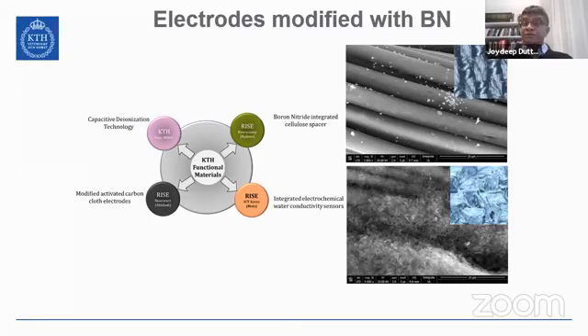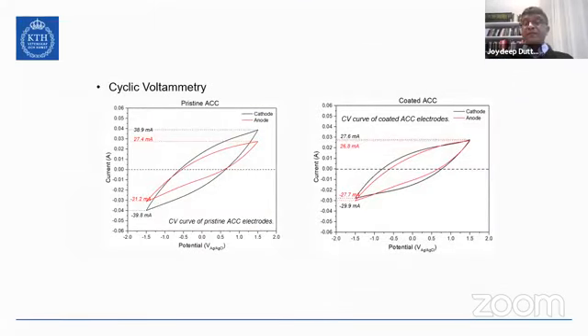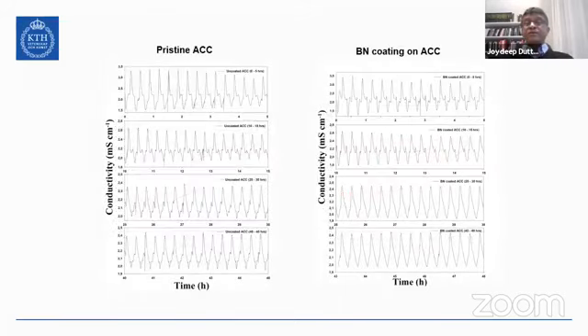Boron nitride is known to have a very high dielectric constant. And we tested long-term stability of it. And it seems that you can increase the capacitance, and also, we are able to have long-term stability of these electrodes at higher voltages.